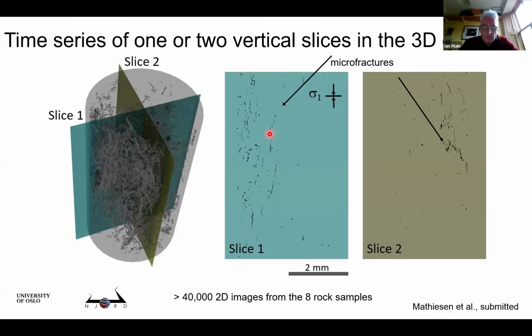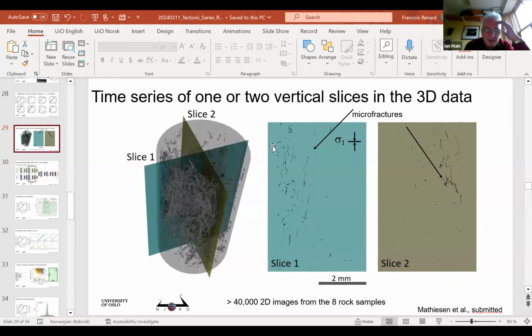That's something that the machine learning model has learned, that when it's finding those kinds of aligned sets of fractures, which may be connected in 3D. That's another question, the 2D, 3D thing, whether that's contiguous in 3D, but it's actually en echelon in 2D. But somehow the information in 3D is present, because from this sample we take 2 images, but then we can rotate these 2 images by an angle like 10 degrees, 10 degrees, 10 degrees. So at the end, the 3D information of this sample will be present in a series of images. It's just that the 3D information is present in a series of 2D images.